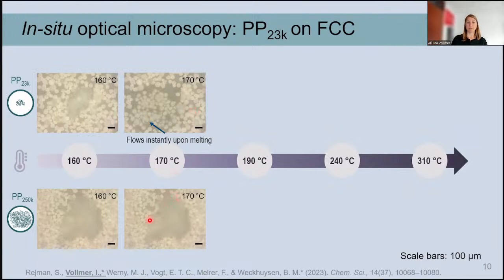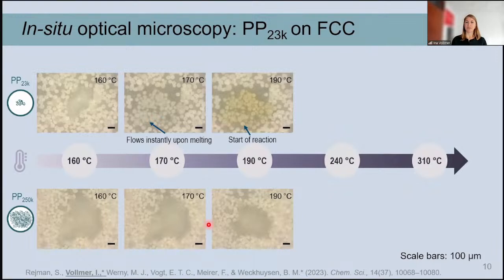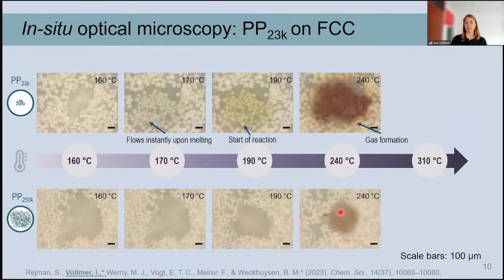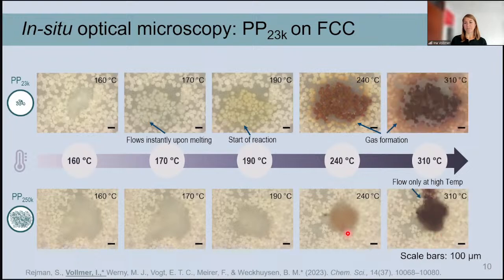While at the bottom, we see that this blob of plastic is becoming a little bit more round, but it is not flowing into the catalyst bed. So there's no contact or very little contact with the catalyst particles. And this continues upon heating up. The polymer at the bottom is just curling up more and more. And at some point, you see that the bottom of this blob is reacting with the catalyst particles, but only at a very small contact area. And so this whole thing is very inefficient.